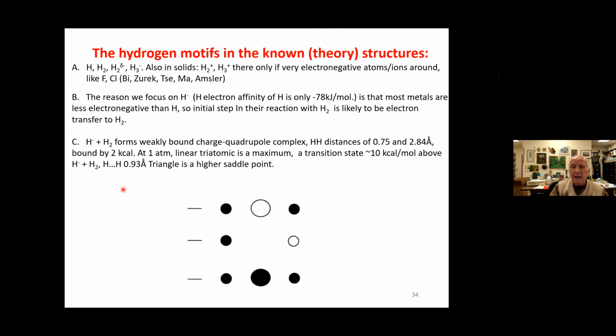But under pressure, it's certainly possible to transfer electrons to hydrogen. H minus, if it were formed, forms only a weak complex with H2. Essentially, the H minus stays 2.8 angstroms away from an essentially unperturbed H2 to give a charged quadrupole complex.